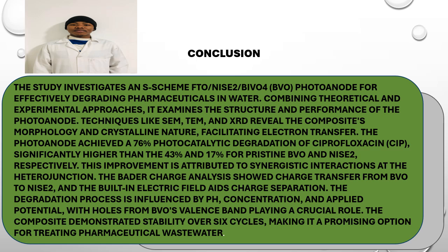So, as we have studied the photoanode made by FTO/NiSe2/BiVO4, which effectively breaks down pharmaceuticals in water, our research combined theoretical and experimental methods to analyze the method and its structure based on performance. The key findings were that the composite achieved 76% degradation of ciprofloxacin, abbreviated as CIP, outperforming the individual components.